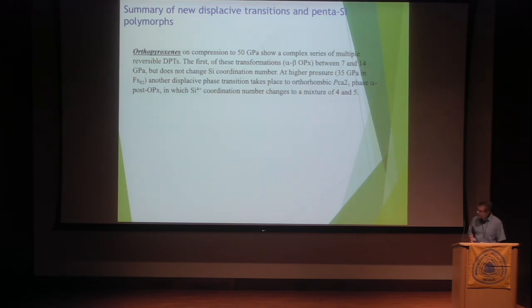So to summarize, we've explored the whole family of pyroxenes as a function of composition. We've explored it to a pressure of about 50 gigapascals at low temperatures, at temperatures that might be relevant to cold subducting slabs. And we found a number of discontinuities, number of structural phase changes which haven't been known before, but might be relevant for explaining the stagnation of subducting slabs.